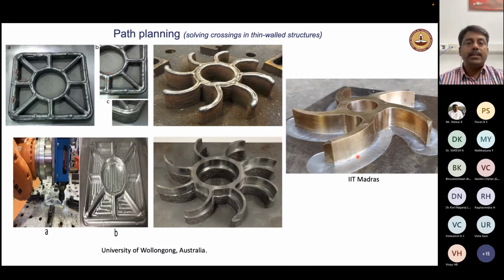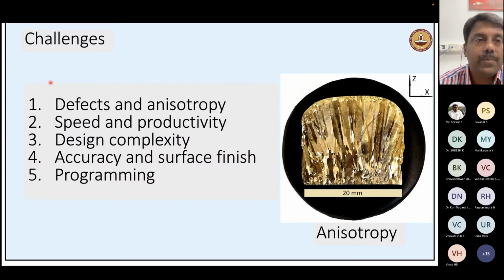Good. And these are some example components we printed using the DED process at a collaborator's place, using the technique I explained earlier. We can also manipulate slicing and path planning strategies to our advantage, because path planning is important for changing the cooling rates and temperature gradients prevailing in the solidifying molten pool. By carefully manipulating these, we can also control the microstructures, and therefore the properties, of the component.